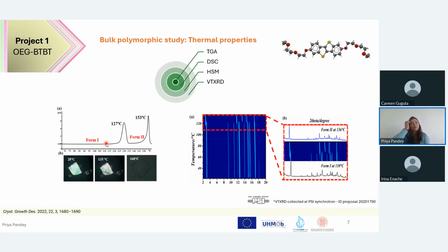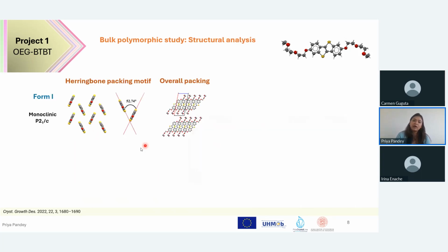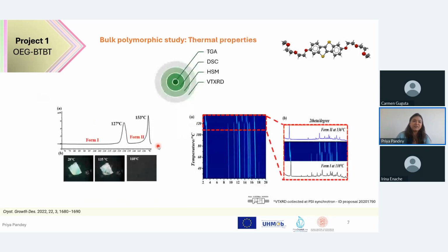So in the bulk polymorphic study, first we go through the thermal property characterization. First, we have to see how stable the molecule is, then see if there is any thermotropic transition. In this case, you can see form 1, which is a room temperature form, transforms to a high temperature form. And this can be seen from 3 different techniques that we have attempted.